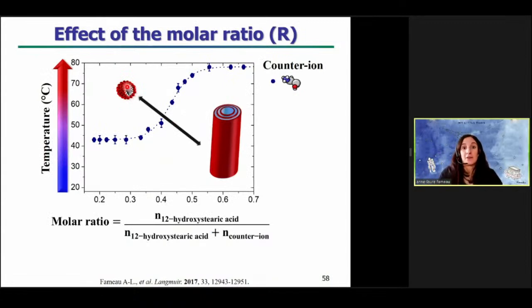Then we studied another parameter, the effect of the molar ratio, and we defined the molar ratio as the number of moles of the fatty acid divided by the total number of moles inside our system. Here you can see the result for the counterion with 2 carbons. On the graph where the temperature is plotted as a function of the molar ratio, you can see that at low molar ratio, where we are in excess of counterion, the temperature transition is around 42 degrees. Then you observe a sharp increase by increasing the molar ratio until a plateau is reached around 78 degrees.